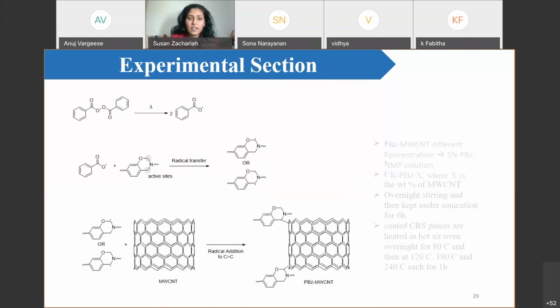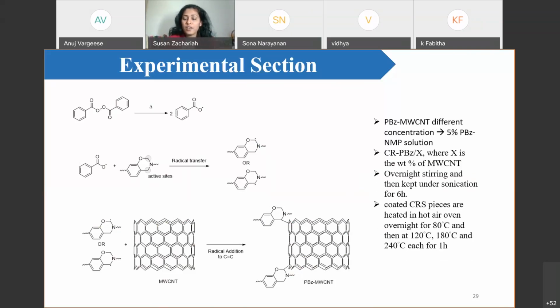After making the PBZ multi-wall CNT, this is added onto the PBZ solution, mixed properly, and coated over CRS. We found that, compared to the non-functionalized one, this functionalized CNT gave a good dispersion on the surface and good adhesion with the polymer.